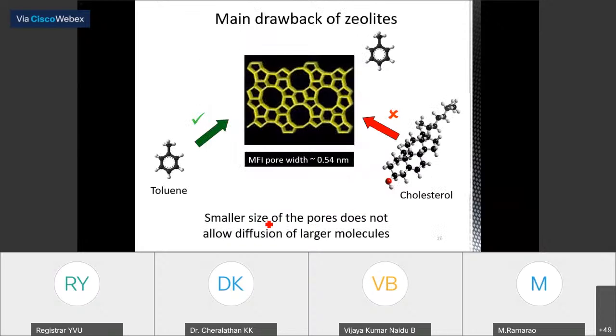Simply, you can understand this by looking at this slide. If you take a zeolite like MFI zeolite, which has a pore width of about 0.54 nanometer, and if you pass toluene, toluene easily passes through the zeolite crystal and comes out. Via the pores, it will enter and then it will come out. It will diffuse into the catalyst crystal of this zeolite. But at the same time, if you think about cholesterol, which is a larger molecule, it cannot be processed by the zeolite because it won't enter into the pores at all because of its larger size. So this is one of the main drawbacks of zeolites.